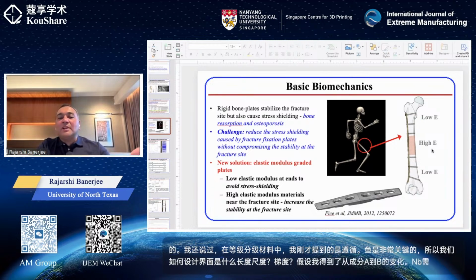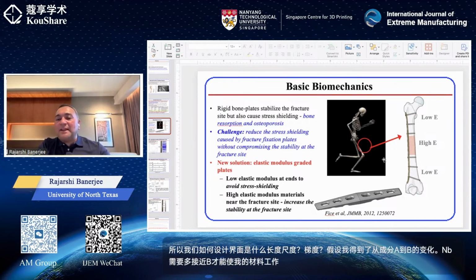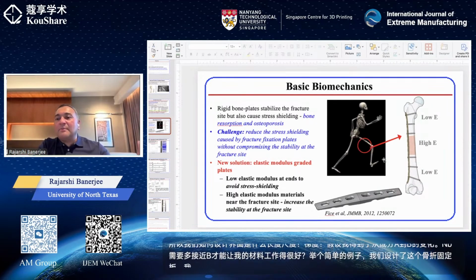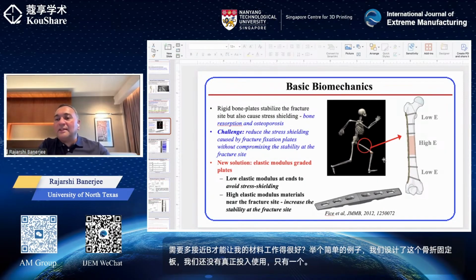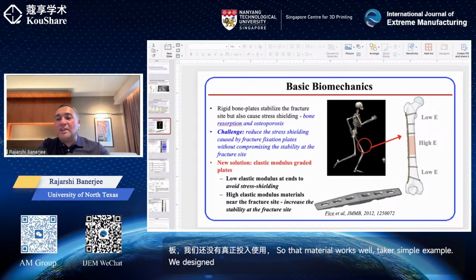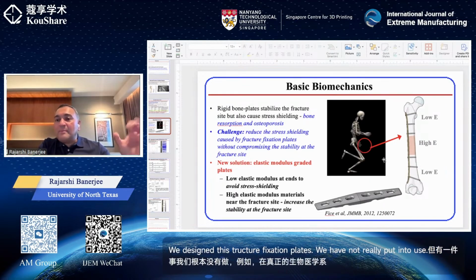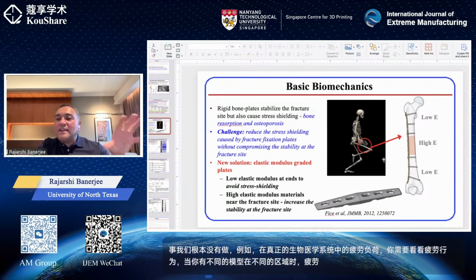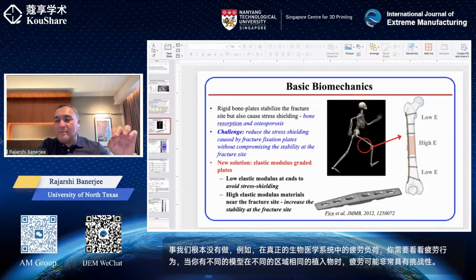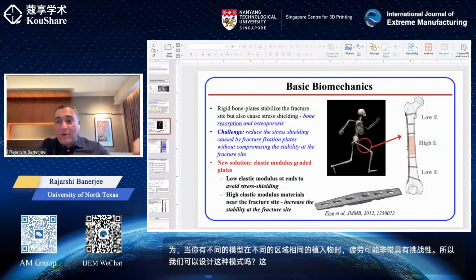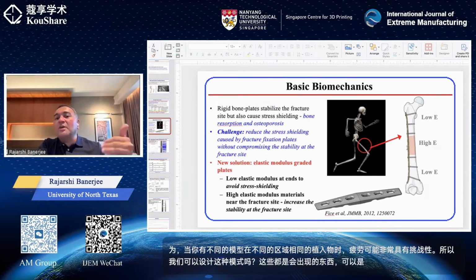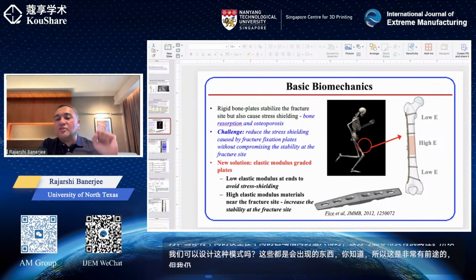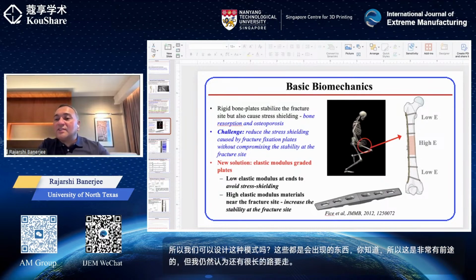Take a simple example. We designed this fracture fixation plate. We have not really put it into use, but one thing we have not done at all is, for example, fatigue loading. In a real biomedical system, you will need to look at the fatigue behavior, and fatigue can be very challenging when you have different moduli in different regions of the same implant. So can we design that better? Those are the types of things that will come up. It's very promising, but I still think there's a long way to go in terms of actually applying them in an industrially acceptable manner.